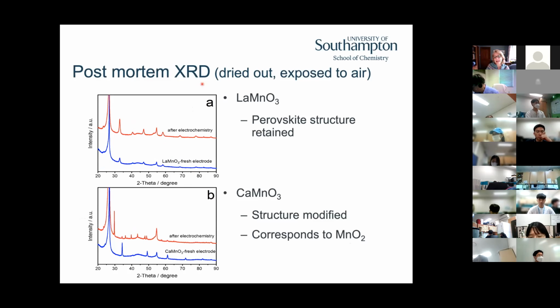And we can see that when we look in the post-mortem XRD. So we dried out the electrodes and looked at them. After the electrochemistry, we've still retained the perovskite structure. But here, for the calcium, we don't. And we're really making something that's much more like manganese oxide.